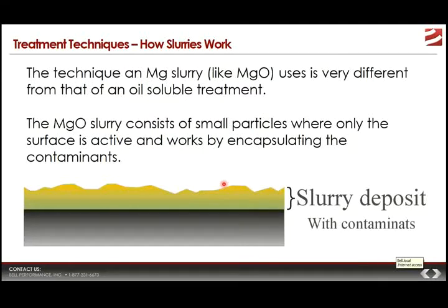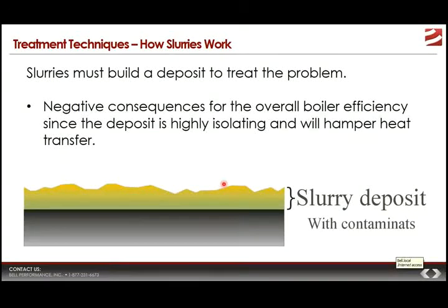So what does the magnesium oxide slurry do? It's small particles. Because it's just little particles of MgO, they're only active on the surface. It basically works by encapsulating the contaminants in a layer of magnesium oxide buildup. Now, what can it do and what can't it do? Well, in order to treat the problem, they have to build the deposit up. The deposit then shields the old deposit from contact and exposure with SO2 and SO3 gases. So it physically interrupts the contact between what would have been catalytic deposits and the sulfur gases that are seeking to be catalytically affected by it.